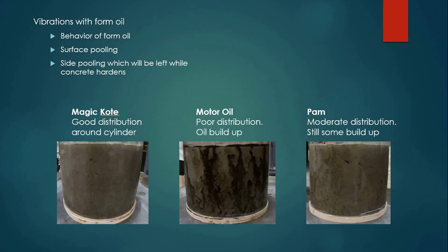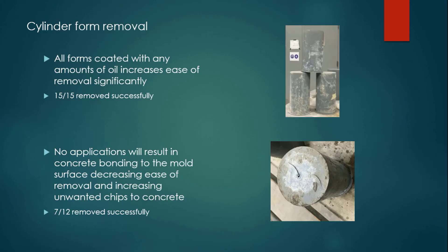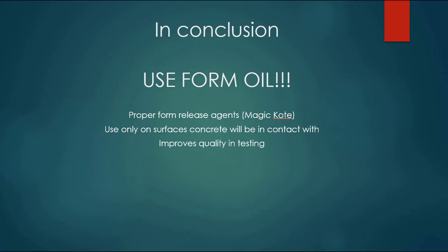In conclusion, there was a big difference between the commercial form oils and those that aren't. The commercial form oil didn't eat away at the surface and didn't leave buildup — it just performed much better. Any form oil used on the cylinders made demolding much, much easier, and those that didn't have form oil, about half of them had failures. We didn't see any reduction in performance of the concrete unless heavy amounts of form oil were mixed in. In conclusion, form oil is a good thing — we should be using it. Thank you.